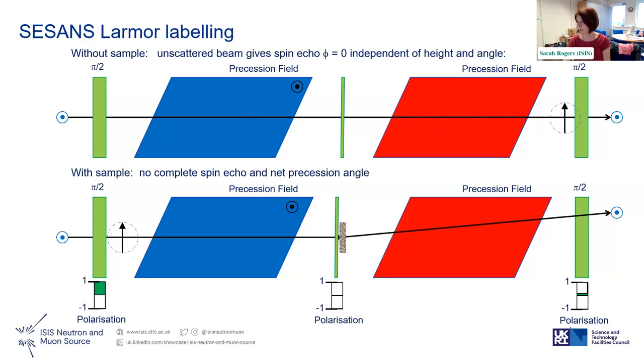Then if you have a sample in the way, the bottom thing happens. So you start to precess your neutron, spinning away, it interacts with the sample. You then try and unwind it. But when you unwind it, the polarization is now not zero. And you can relate that polarization to basically a G of R, a real space. So it sounds very complicated, and it is quite a complicated setup, but it basically allows you to probe larger length scales, but without having to have these very, very long beam lines.